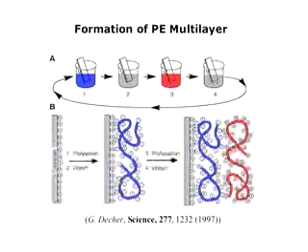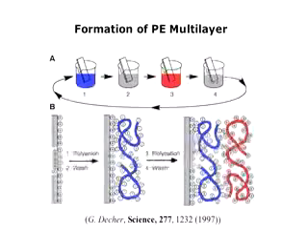Another system I am interested in is polyelectrolytes. In contrast to most neutral polymers, these charged polymers are water-soluble and therefore have lots of great interest in biological and industrial applications. For example, most biopolymers such as DNA are polyelectrolytes. But these materials are difficult to study because there are multiple length scales in the system, coming from both long-range electrostatic interactions and short-range excluded volume interactions.